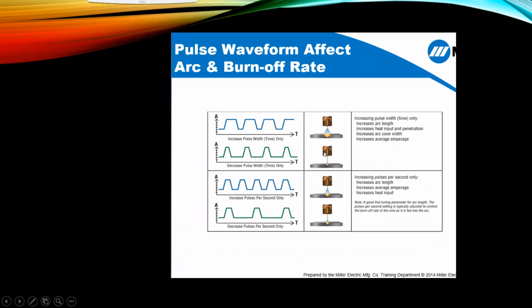And I really like this slide because it demonstrates a little more information as to what we're going to see when we start changing some of those variables. What's really nice is the machine's being synergic. When you're running pulse, you don't necessarily have to worry about all these variables, but it's good to have an understanding of what is going on. So looking here, as we increase our pulses per second, one of the things it's going to do is increase that arc length from the end of the wire to the puddle, and it's also going to increase our average amperage and also increase the heat input.